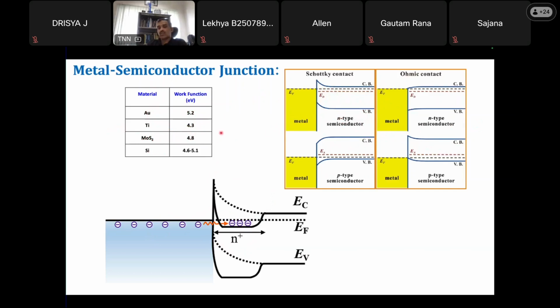Similarly, for a p-type semiconductor, the thumb rule is exactly the opposite: a higher work function metal needs to be used, because the hole is the major transporting carrier. The energy bending will be that way. So this is a thumb rule for semiconductors in general. You need to use a suitable work function metal to form an ohmic contact junction. Now, how do you address this in a silicon semiconductor? To address this issue, what people do is, before the silicon-metal contact formation, at the junction they do an ion implantation or so to make it a degenerate semiconductor.